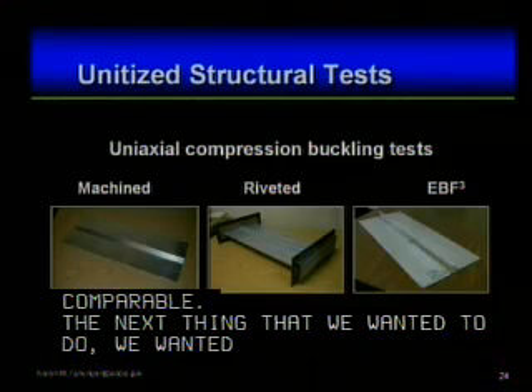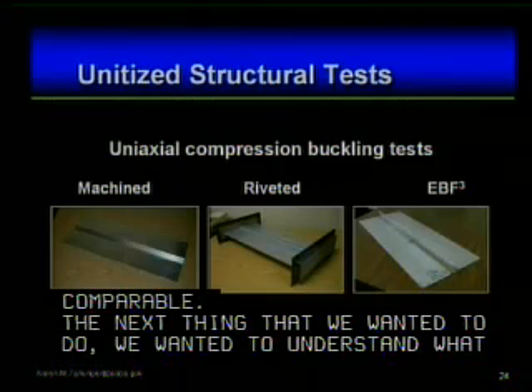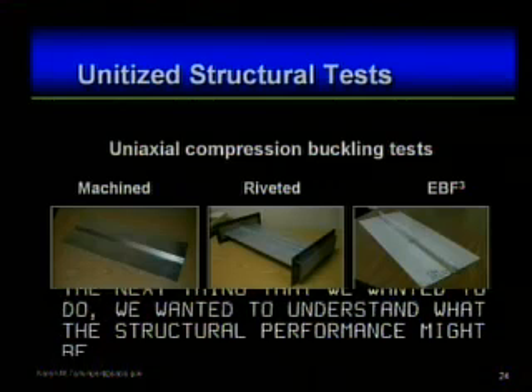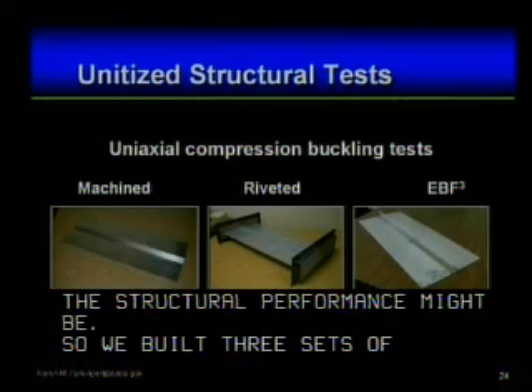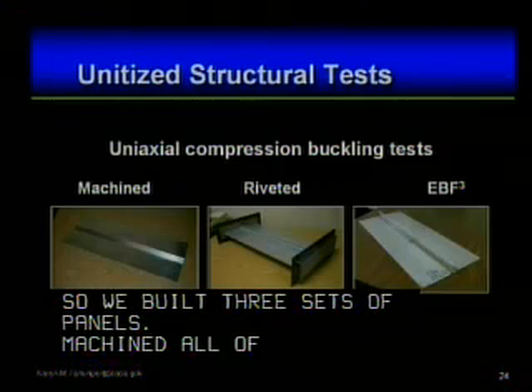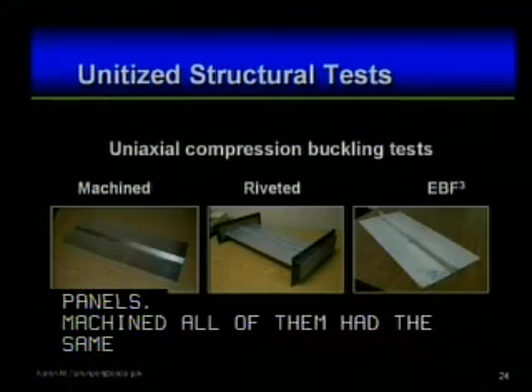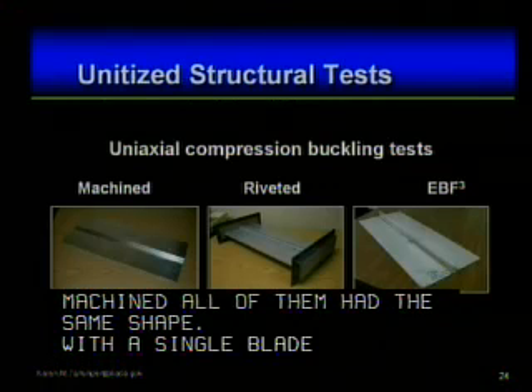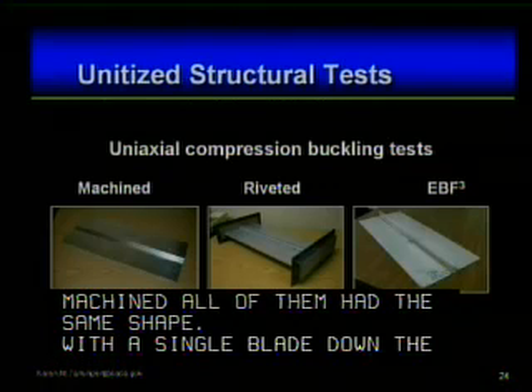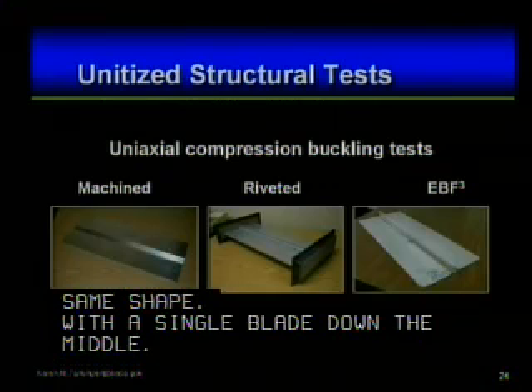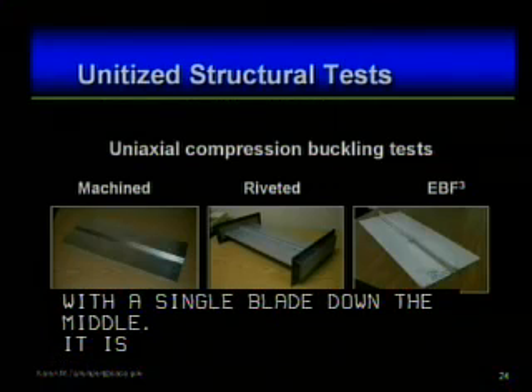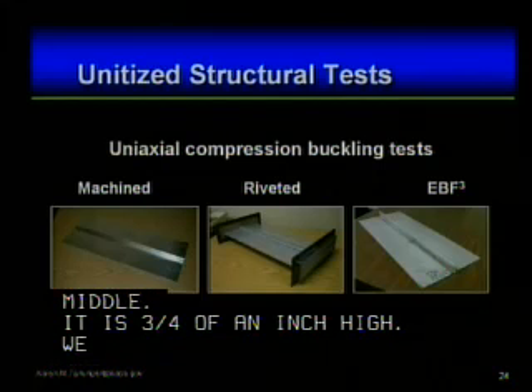And so we built three sets of machined panels. All of them had the same final geometry. These panels are on the order of 24 inches long and 8 inches wide, with a single blade stiffener down the middle that's about 3/4 of an inch high. For the machined one, we started with 1 inch thick plate and machined it down, leaving the blade stiffener integral to the base plate. For the riveted one, we started with 1/4 inch thick base plate and used an L bracket, riveted on to give us the blade stiffener.